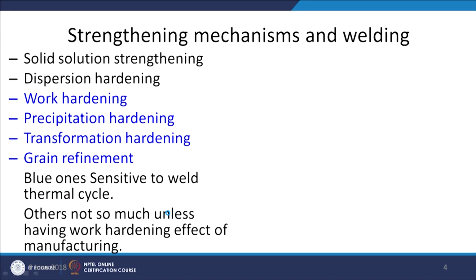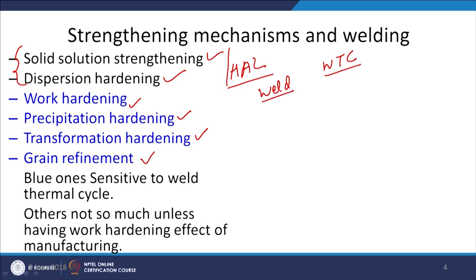So, these were all the strengthening mechanisms like solid solution strengthening, dispersion hardening, work hardening, precipitation hardening, transformation hardening, and the grain refinement. So, if you see the first two strengthening mechanisms, solid solution strengthening and dispersion hardening, the HAZ of the weld is not much affected by the weld thermal cycle if the metal is strengthened by the dispersion hardening and the solid solution strengthening mechanism. But in case of the weld of these two, the weld metal of the dispersion hardened and the solid solution strengthened metal systems will be of somewhat lower strength, and dispersion hardened metal in case of the fusion welding may have the defect formation tendency. But the HAZ properties will not be appreciably affected.